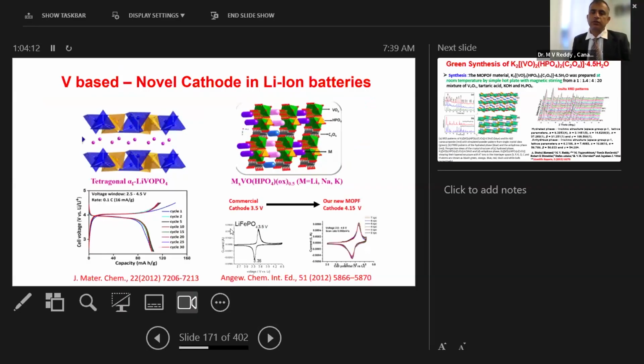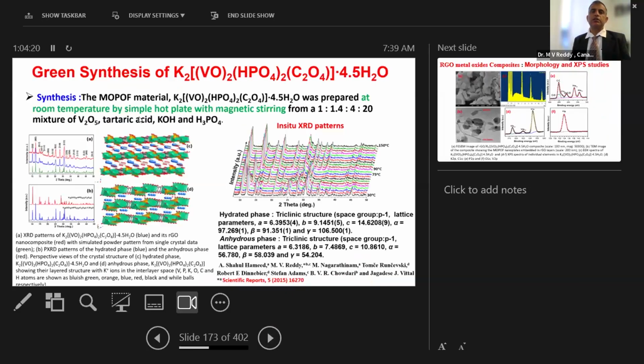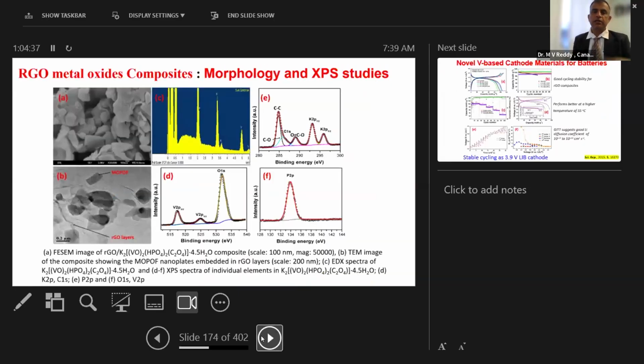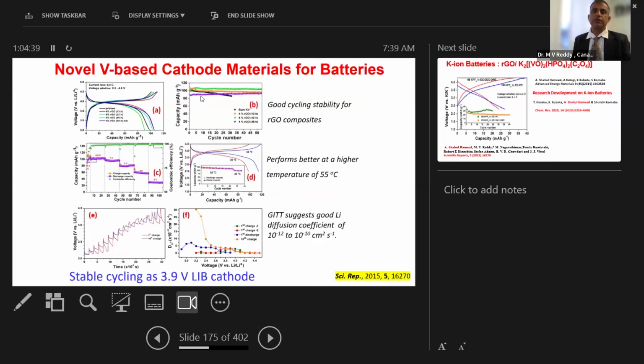So when I compare to lithium iron phosphate, nearly 4.15 volts we are getting, so reasonably good voltage. Again, we try to prepare the sample with a simple approach, with a simple magnetic hot plate stirring. The only issue is the water. We have to get rid of the water. We need to heat the sample to nearly 150 degrees to remove it. Again, we can characterize them. And capacity-wise it is a little bit limited, nearly 110 is what we are getting.